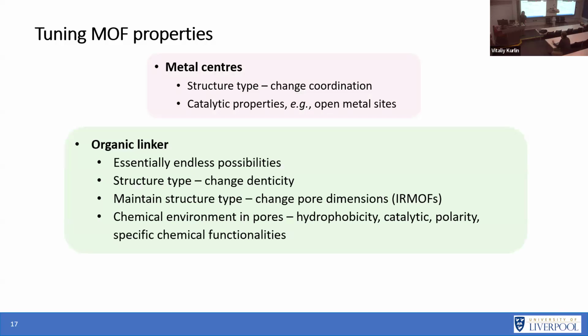Changing the organic linker is a really, really massive way to change your MOF, and that's typically how people will change the properties. And as it says here, there's essentially endless possibilities. So you can change the structure type. You can also keep the structure type. So we mentioned before about this isoreticular series. You can keep the same structure type, but change the pore dimensions. You can also change the chemical environment inside the pores so they can be more hydrophilic, more hydrophobic. They can have more catalytic activity. And you can also introduce specific chemical functionalities based on the linker that you've put in there.